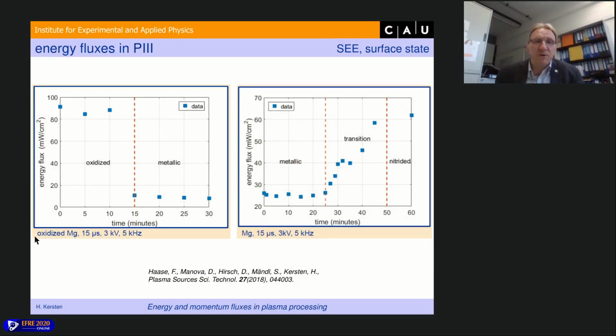For instance, if we use an oxidized magnesium substrate for the PIII, then at the beginning, so the first 10 to 15 minutes, there was about 90 milliwatt per square centimeter. But then suddenly there is a decrease in the energy flux to only about 10 milliwatt per square centimeter. This is because during the sputtering, the substrate is cleaned. And so we have here an oxidized mode, and here we have the metallic mode. And of course, in an oxidized mode, the secondary electron emission is much higher than in a metallic mode. And that we can really see in the energy influx. So it's a very simple method, but you can get this information.